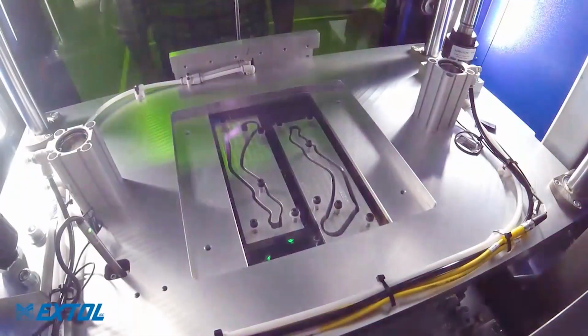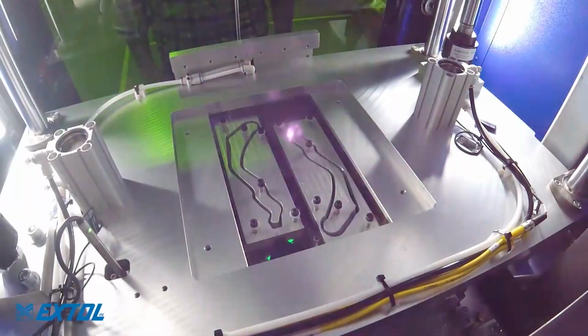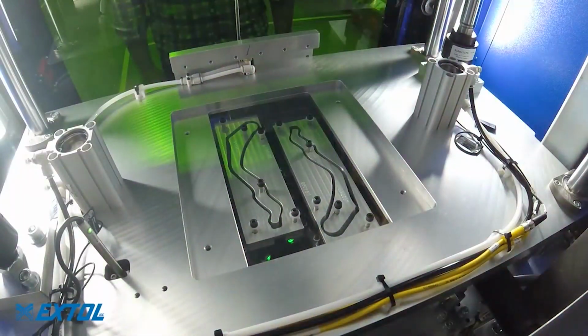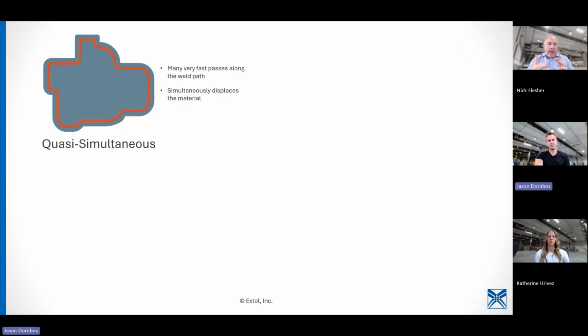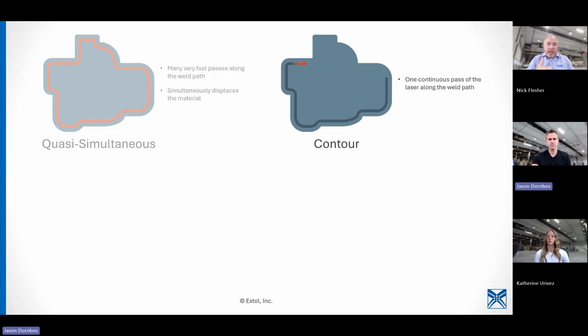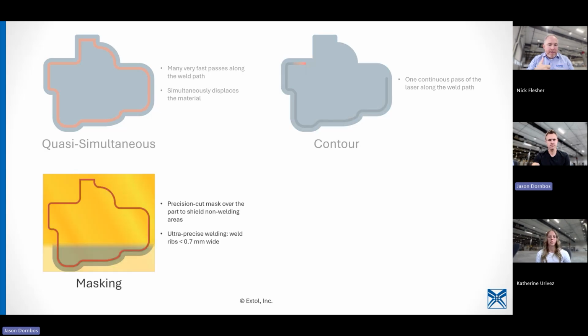Again, that laser's kind of jumping around, but what it's actually doing is tracing that with a 6 millimeter beam spot or 5 millimeter beam spot. So you've got quasi-simultaneous. You have contour welding. Contour welding is one continuous pass along the laser. This can be effective for smaller parts. Larger parts can build in some stresses, and we've seen that it can be effective most of the time, but sometimes you need quasi-simultaneous.